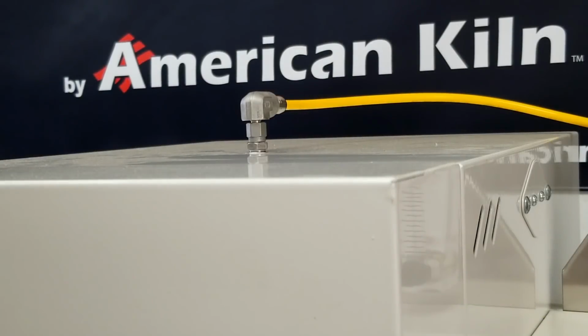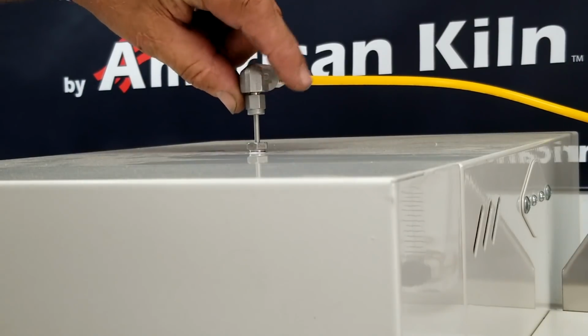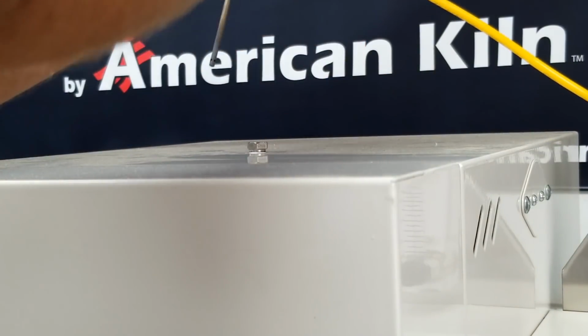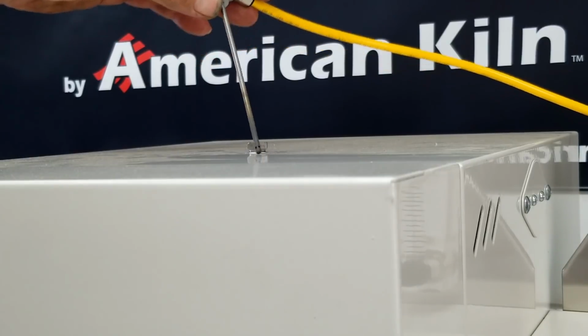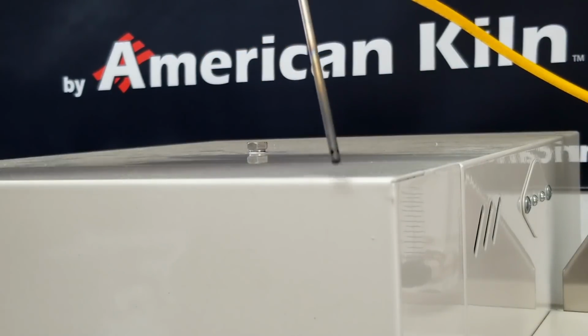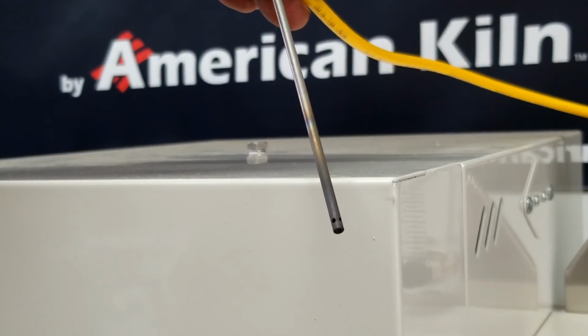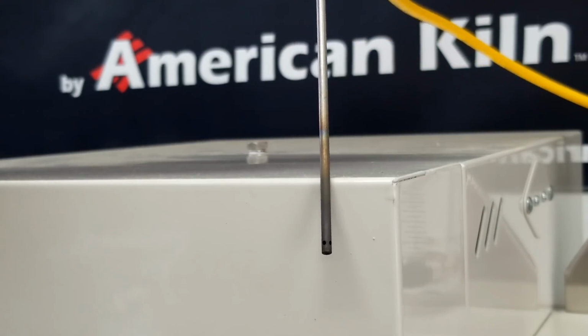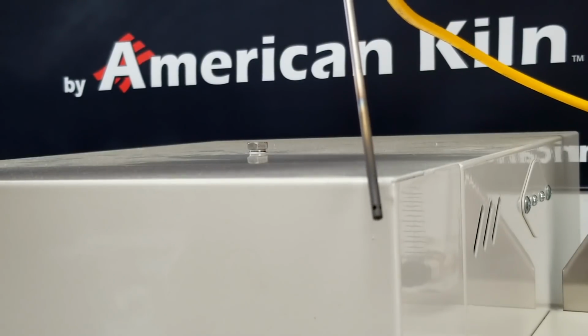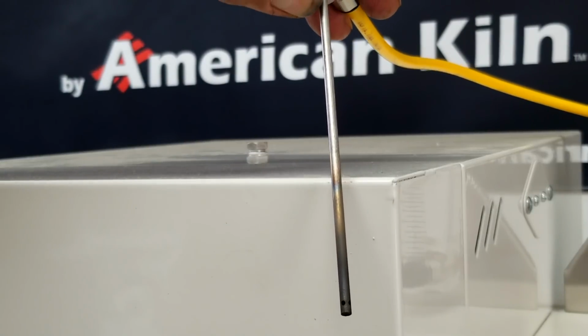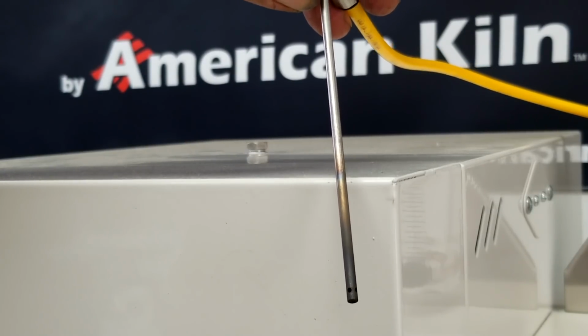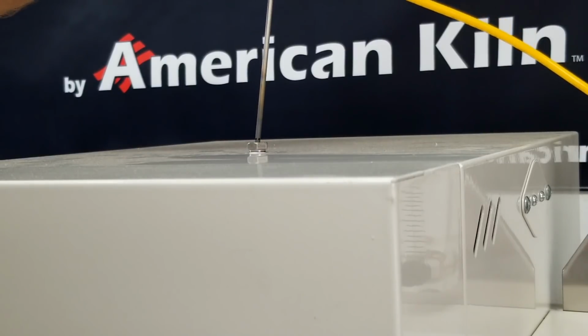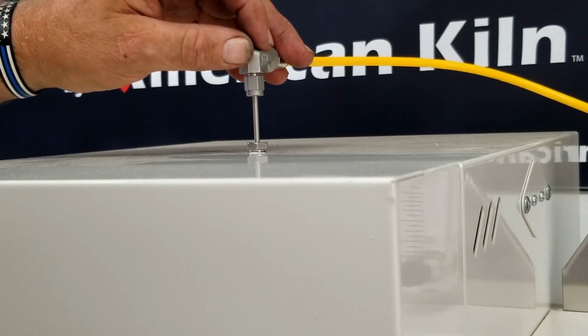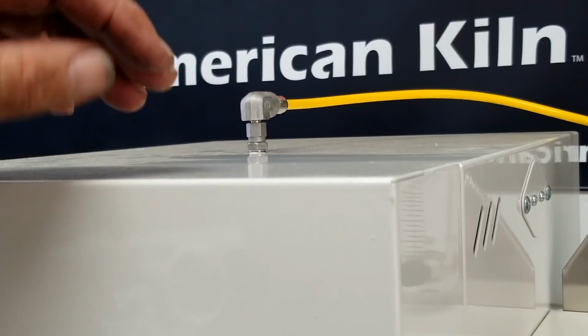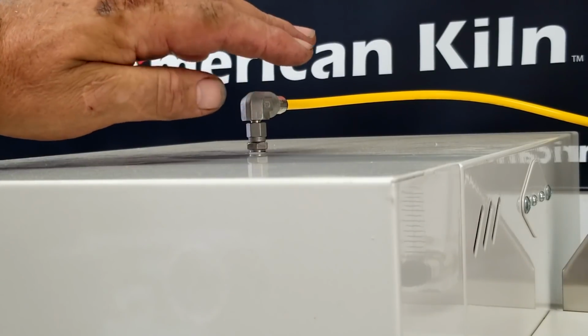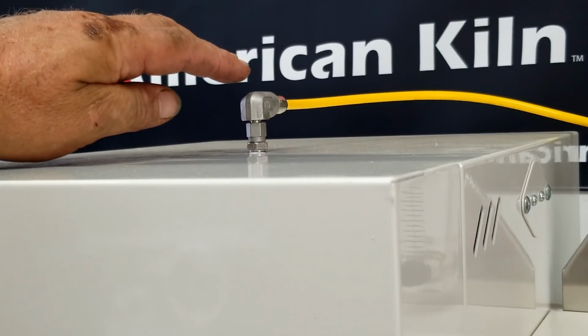Okay, we're done with our cycle, and we can take a look at what this argon tube looks like. There it is there. Discolored on the end, no distortion, no scale. The Inconel holds up well. You can see the temperature gradient across there. But we've tested it with and without argon both, without cleaning the needle or the tube. So I'm thinking you can leave this in all the time, whether you use argon or not.